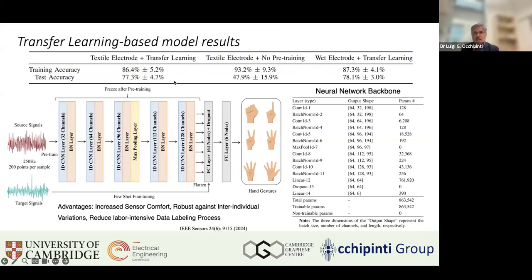And the results are quite comparable, meaning that we could achieve similar results to the gold standard wet electrodes based EMG hand gesture recognition with our dry electrode, of course removing the need of gel. The impact of this to the user, who will of course prefer a dry electrode, besides the fact that the gel electrolytes tend to dry out over time. So it is well known that for long-term measurement, dry electrodes should be preferred.